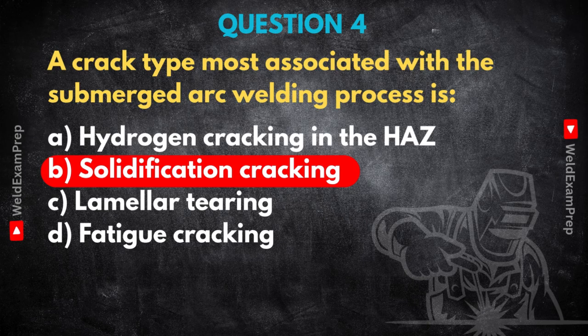Well, solidification cracking, or hot cracking, happens while the weld metal is actually solidifying, not afterwards when it's cold. It happens because certain things, impurities like sulfur or phosphorus, tend to have lower melting points. They're the last bits to freeze as the weld pool cools. Right. So as the main bulk of the weld metal solidifies and shrinks, these low melting point liquids get trapped between the solidifying grains, and they get pulled apart by the shrinkage stresses, forming cracks right along those boundaries. Ah, I see. They create weak paths.